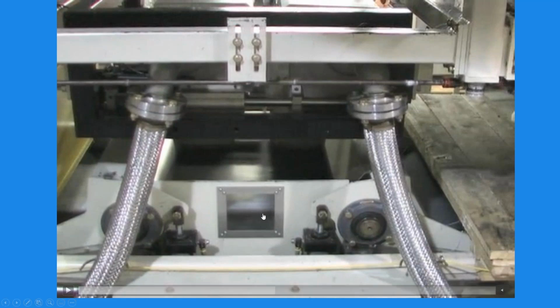Unfortunately, the belt moves so fast that it does pull the fibers in the machine direction a little bit. So you don't get a perfect fiber distribution in all axial directions, but you do get about 1.3 to 1. Just imagine these fibers coming down. They have to slow down, so they start swirling around and wiggling back and forth this way and that way. And that's what helps with the randomization.